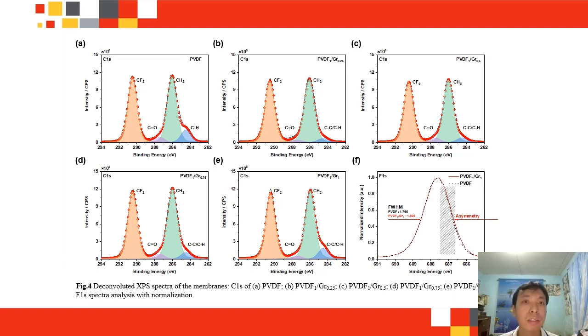Next, as the graphene content increased, notable changes were observed in the chemical structure. Specifically, the intensity of overlapping CC and CH bonds strengthened, reflecting graphene's influence on the membrane's chemical composition. Additionally, the integrated area ratio of CH2 to CF2 increased, indicating enhanced interfacial interactions between PVDF molecular chains and graphene. This interaction is critical as it contributes to the structural transformation from the alpha phase to the electroactive beta phase, which is critical for the membrane's piezoelectric properties.